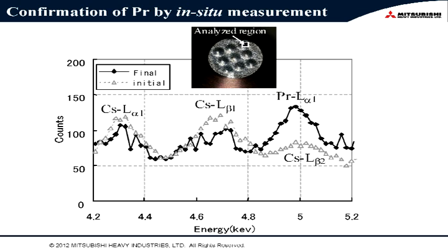This is the result confirming the precipitation by in-situ measurement. This is X-ray fluorescence energy and count. The white one corresponds to the initial state before permeation, and the black one corresponds to after permeation. We can see that after permeation, the praseodymium X-ray fluorescence increases. So at this point, the transmutation reaction of cesium into praseodymium occurred. And this reaction was confirmed by researchers at Mitsubishi Heavy Industries and other university researchers.